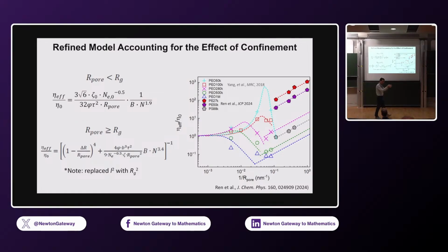There's a regime where the dead zone on the pore affects the polymer infiltration, and then this is the reptation in the capillary pressure-driven flow, and then there's a region where the confinement affects many of the parameters that affect how these polymers are behaving in these pores.